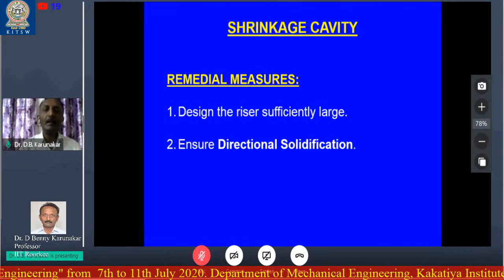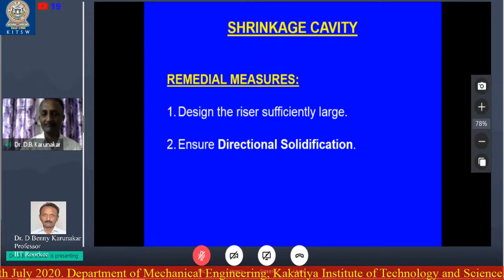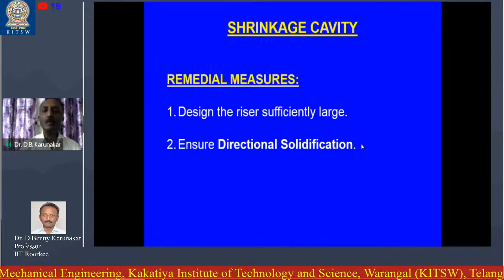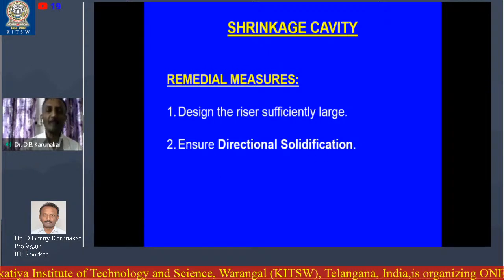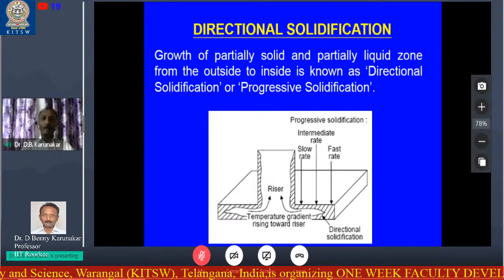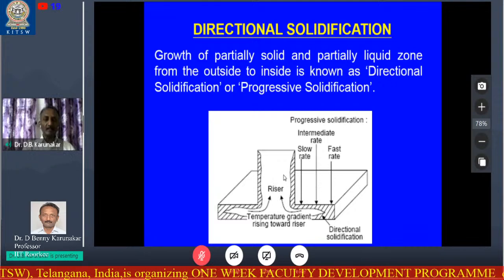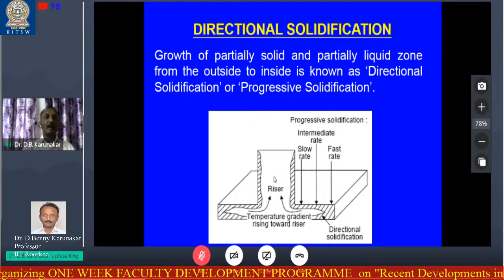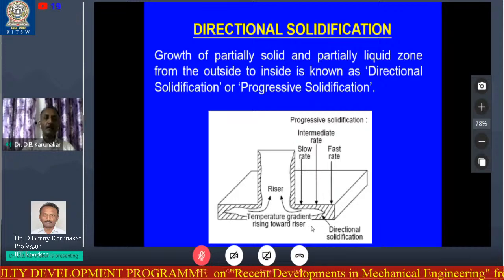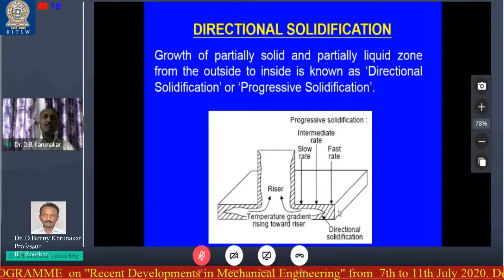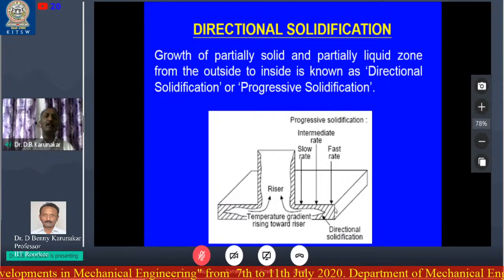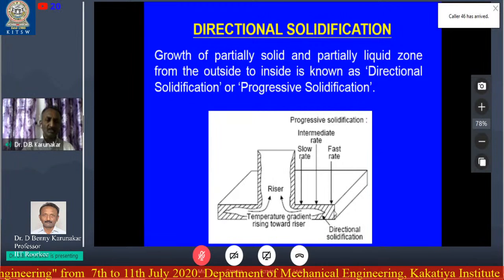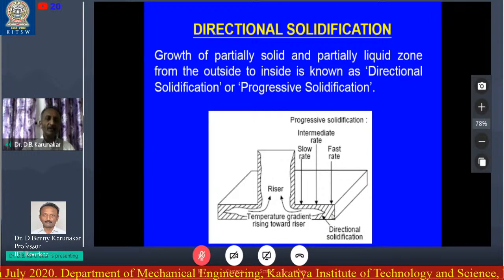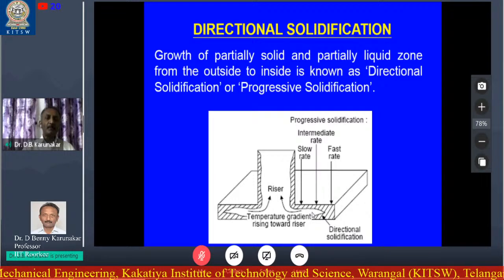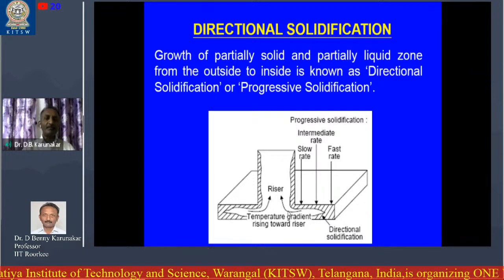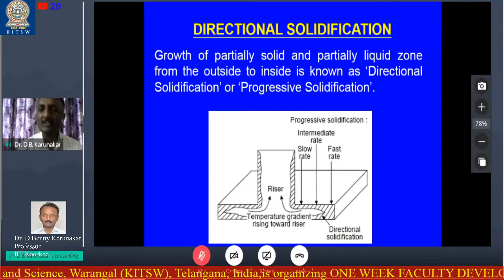Remedial measures. Design the riser sufficiently larger. And second thing is ensure directional solidification. What is this directional solidification? Now you see here, this is the casting and this is the riser. Now, the solidification starts from the end of the casting, near the mold wall. You see, it is starting from right to left, like this. The solidification is propagating. This is known as the directional solidification.